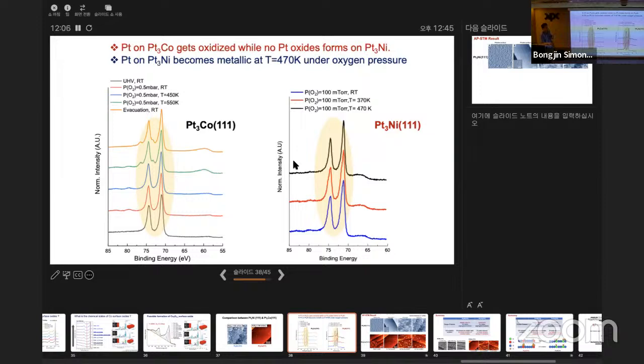That's actually very small, remains small, not getting enlarged. And this is another reason that you don't see the oxidation of the platinum. That's not enough to disturb the platinum, but in the cobalt, it does. When I talk about this, not scientifically, just roughly with the electrochemists, they said platinum-3 cobalt is more stable in some respects. Once you form an oxide, this one will become a more stable, more solid oxide than the nickel oxide. So at the moment we are talking to the theoreticians and trying to figure out what the chemical state is that this one is coming from.